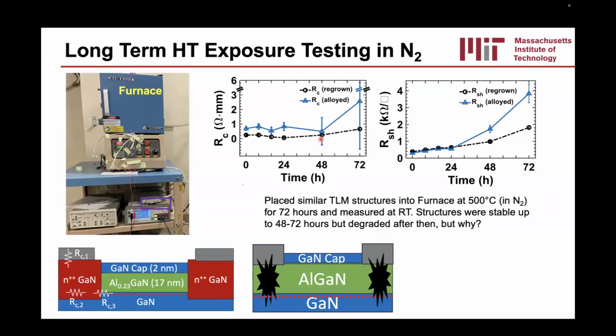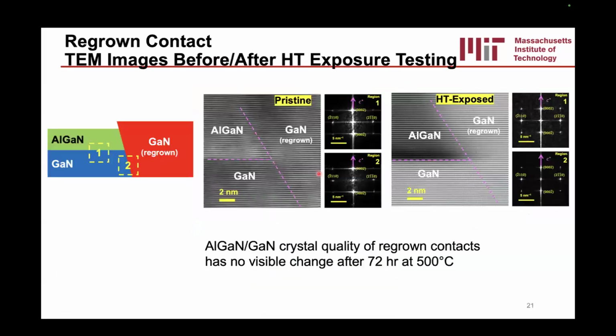We can see that at around 48 hours or so, both the sheet resistance and the contact resistance start to dramatically increase, and the error bars get very high as well. And so it's stable up to then, but it starts to degrade afterwards. So we wanted to understand what is going on here. From that, we did a few microscopy studies where we looked at TEM images of pristine samples and samples that have been through the full 72-hour 500C exposure process.